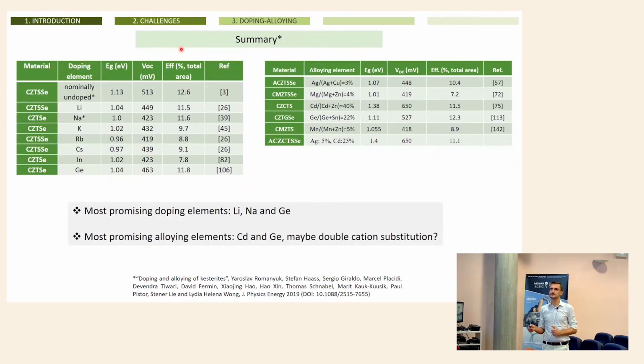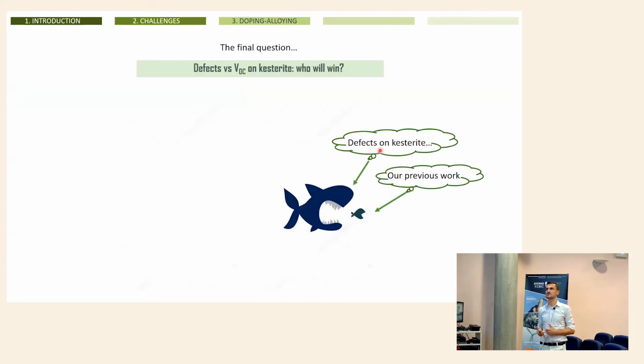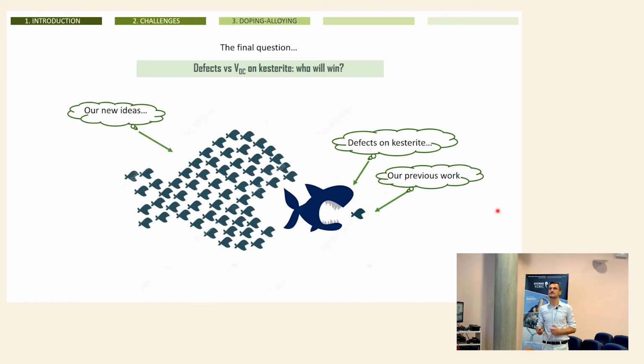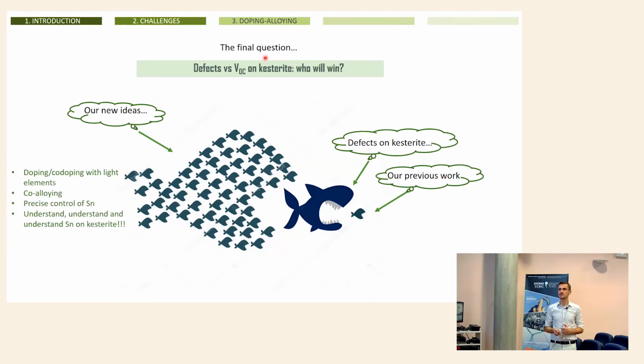As a summary, all these possible elements and even many more have been tried for kesterite. The most promising doping elements are lithium, sodium, and germanium, and the alloying elements are cadmium and germanium. Maybe a combination of them can give very nice surprises in the future. But for the moment, these are the defects in kesterite that are always eating our previous work. And after several years, we don't have real progress on efficiency. Let's hope that in the future our new ideas will really tackle these defects in kesterite and we can achieve efficiencies beyond 20%.